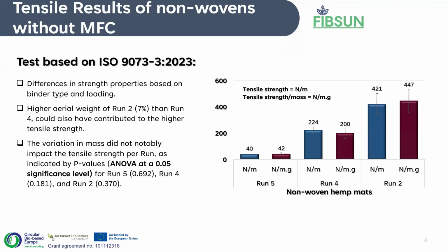non-wovens from Comatex, and our goal is also to define the DNA of the non-woven. So we just measure the tensile properties of this non-woven. And in any case, we could see the variation in terms of first the binder type, that with the epoxy resin, the strength properties are pretty low, which is perhaps understandable when you use a powder in combination with fiber.